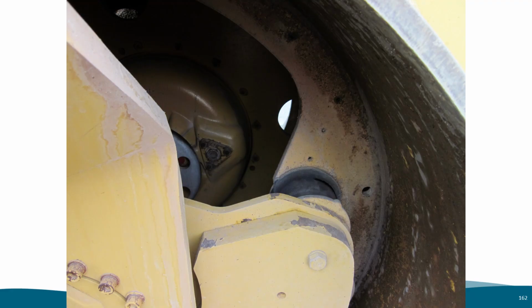Here is a close-up of the drum, looking at the vibratory part of the roller. Frequency is how fast the drum is vibrating. Amplitude is the measurement of how far you are driving the drum up and down the asphalt mat. Note, if the aggregate is breaking, the amplitude may be set too high. Generally, the contractor likes high amplitude for best results.